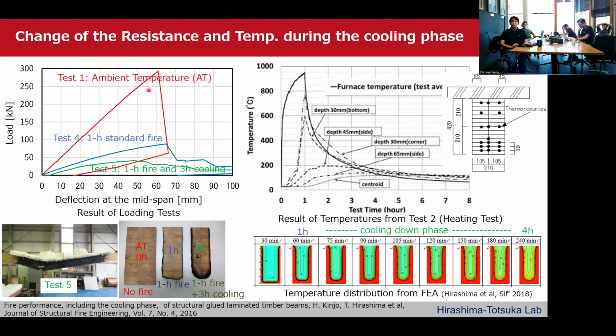This figure shows the results of the loading test. The maximum load just after heating for 1 hour was about 30% of the maximum load at ambient temperature. Furthermore, when left to cool for a further 3 hours, the maximum load decreased to about half of the maximum load just after heating for 1 hour.